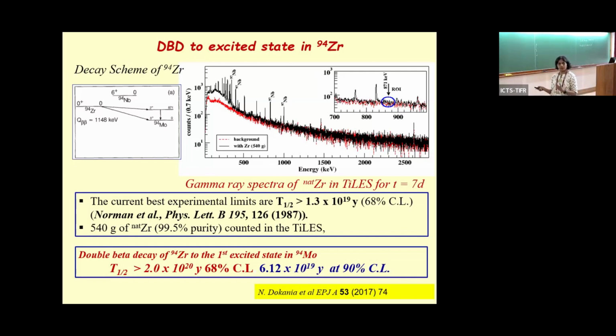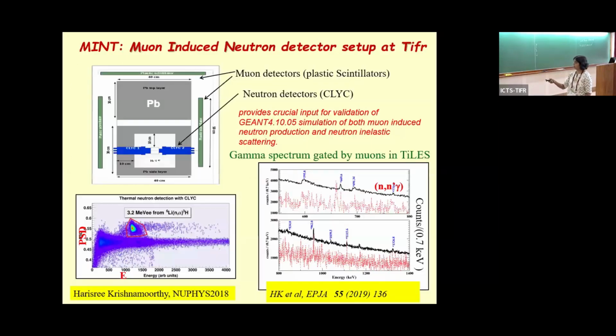Of course we used it even for our sensors and other materials for checking radiopurity, but we also looked at the double beta decay to the excited state. Suppose the 94 zirconium double beta decay can go to the ground state, but can also go to the excited state. If it goes to the excited state, it will decay by a gamma ray of 871 keV, and we tried to look for this gamma ray. Of course, we used natural zirconium, and the probability will be lower and the half-life definitely longer because of the low Q value. But we could put a limit. The earlier limit was about 1.3 times 10^19 years, and even from a sea level measurement we could improve that limit by a significant amount.